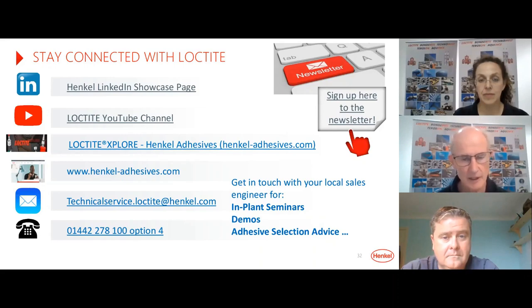Some of our products are rubber toughened, and the adhesive with the rubber fillers helps to arrest and stop that crack propagating. The other thing is what Julie talks about, different flexible adhesives. Where there is a high peel load, we would certainly look at using a more flexible adhesive, which is rubbery, if you like, and that allows you to accommodate a certain amount of flexing between the parts. Okay, thank you.